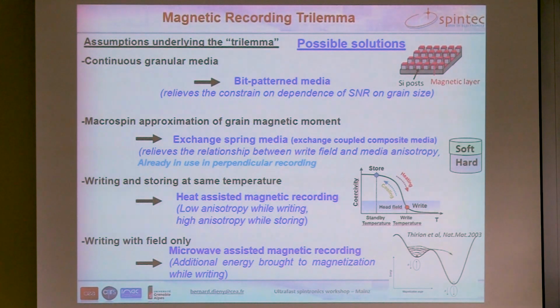And so as a result, we can actually use larger grains. And we no longer need to have something like 10 grains per bit. So as a result, even if we shrink the bits, we can have larger grains just because we have only 1 grain per bit instead of 10 grains per bit.